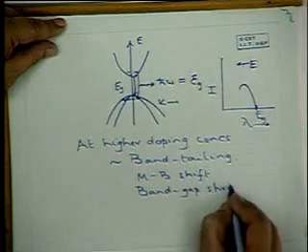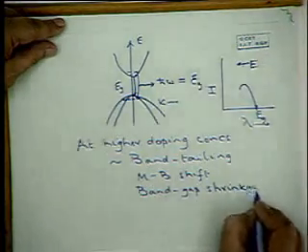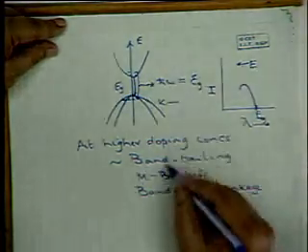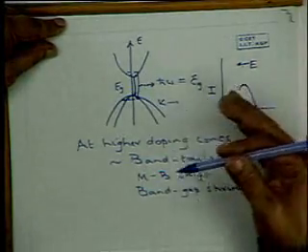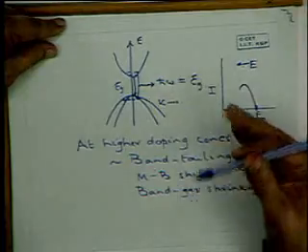This tends to come in at doping concentrations of the order of 10 to the power 17 and higher. The excitonic mechanism is present for low doping concentrations, 10 to the power 13, 10 to the power 14, 10 to the power 15. Band to band is 10 to the power 16, 17, and then at higher doping, all these effects come in.